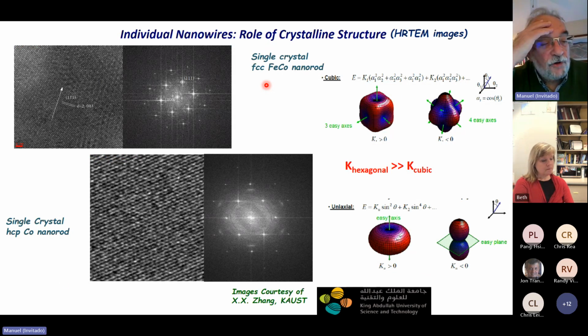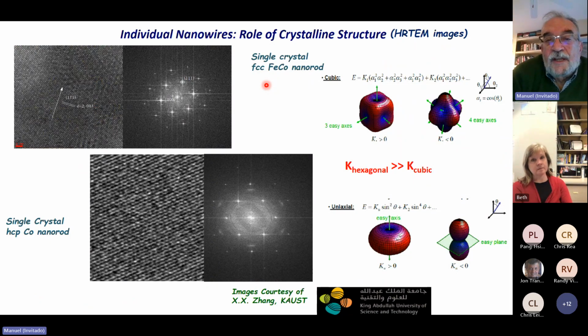Okay, from now on, I'm going to talk just about individual nanowires. The first thing is that, in the case of these nanowires, the role played by the crystalline structure is very important. Here, in the upper part, you see a single crystal with cubic atomic symmetry. It's an iron cobalt nanorod, in this case a longer nanowire, a few microns in length. And at the bottom, we have a single crystal of cobalt, whose structure is hexagonal HCP. I would like to emphasize that the magnetocrystalline anisotropy in a cubic crystal is much smaller than in the case of a hexagonal or uniaxial anisotropy.